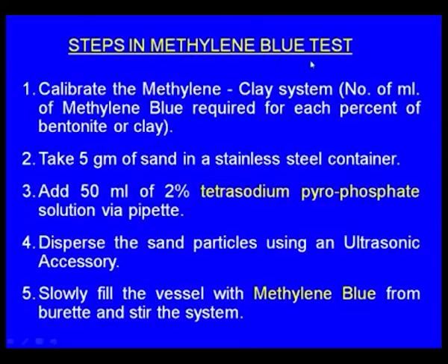Steps in the methylene blue test. First, we have to calibrate the methylene blue with the clay system. This methylene blue solution reacts with the active clay. As long as the active clay is present, the methylene blue will be reacting and we can't see any methylene blue and its effects.